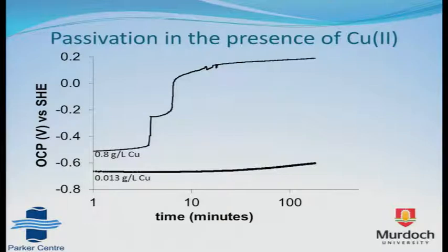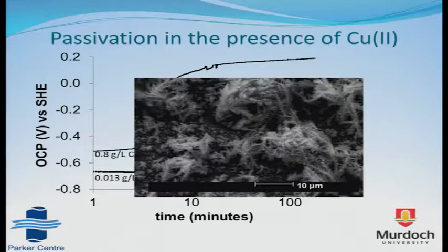So in the presence of copper, in the first case of passivation that has been observed, you can see that at the concentrations of copper, quite low concentrations, which are found at the Yabulu plant, which is the lower curve, the potential of iron versus time doesn't really change much. So it remains in what is known to be the active dissolution region, and at the end of this observation of the iron surface shows that there's been deposition of copper, of metallic copper, onto the iron. These dendrites have been formed whilst the iron is dissolving, so it's been a metal displacement reaction by which the copper is displacing iron and is depositing onto the iron surface whilst the iron is dissolving.